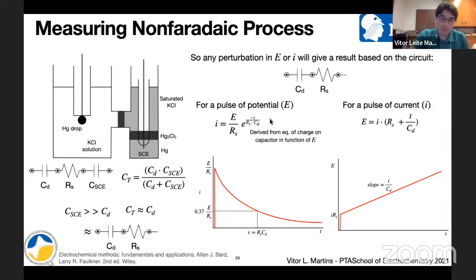So here, respecting this equation, we have that the time will be equal to resistance times capacitance when the current dropped 37%. You see, so this is the first current here. When the current will be 37% of this value, we have this time constant. And this time constant is equal to the resistance times capacitance. This equation also tells us that when the current drops to 5% of this initial value, we have that the time will be equal to 3 times the time constant. All right. So this is just the value that we get from this equation during the variation of time.